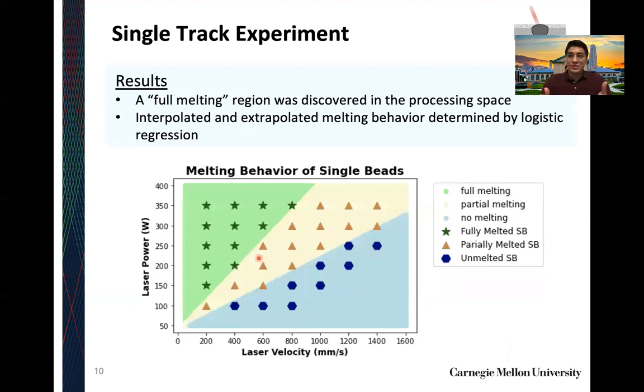Now, with regards to the actual results of these single beads, you see here we labeled all the green stars had full melting. In other words, our tracks were consistent in width and fully continuous. We had partial melting where our tracks perhaps had a very high deviation in width, or were perhaps even discontinuous. And in blue hexagons, we essentially found no melting or no traces of a track whatsoever. And we used a logistic regression analysis to essentially interpolate and extrapolate these results. So that way we have a decent idea of what we would call fully melted regions in green, partially melted regions in yellow, and unmelted regions in light blue.